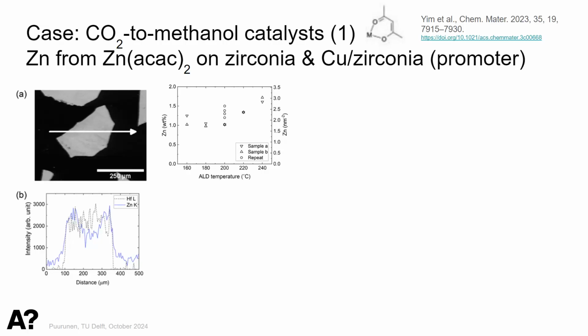But we have had one project where carbon dioxide is hydrogenated to methanol, where we have made catalysts by ALD. We started with zirconia. Why zirconia? Well, in this reaction, per one molecule of methanol, you are making one molecule of water. And you could imagine that that water is problematic to the catalyst in the longer term. And zirconia should be able to handle water better than, for example, alumina that's in the traditional commercial catalyst.